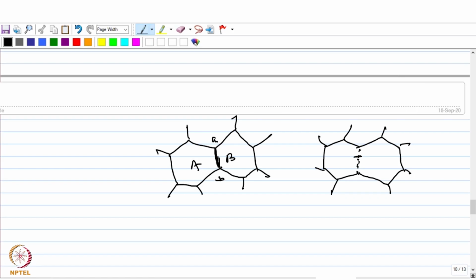So this boundary is going to actually disappear, and these two grains A and B will now merge into one bigger grain. So this is how, as the boundary develops, depending on the character of the boundary, these two grains can coalesce into one bigger grain, and that is how they will grow in size. So these are the different ways of looking at the grain growth phenomena which occurs after the grains are recrystallized. Okay. And as we have discussed before, the grain size basically depends on, of course, the temperature and also the degree of deformation.